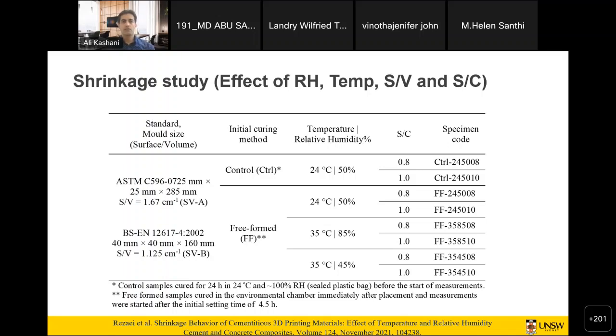In this study, we took the samples out 4.5 hours after molding to get a good initial setting and stiffness, so we could easily take them out of the mold. Then we put them into different temperature and relative humidity conditions: 24 degrees and 50%, which is the standard, and also higher temperature with higher humidity, and higher temperature with similar humidity. Then we monitored the drying shrinkage over up to 90 days and even more than that.